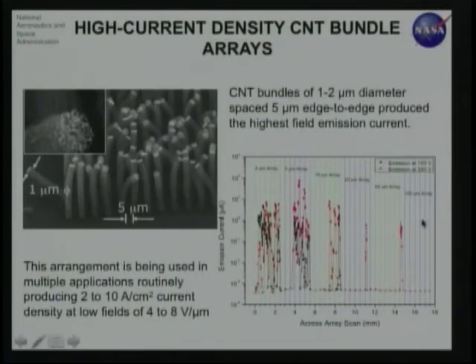So what we ended up making was, after sufficient experimentation, an architecture like this, which looks like each of those is a bundle of carbon nanotubes, about 2 micron or 1 micron in diameter, and they are patterned so that the edge-to-edge distance is about 5 microns. Then you grow them to a few tens of microns to 100 microns tall, and you try different combinations of these on the same sample. So you just change the diameter and the array distance.